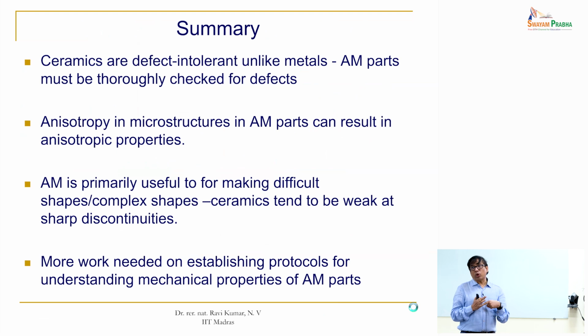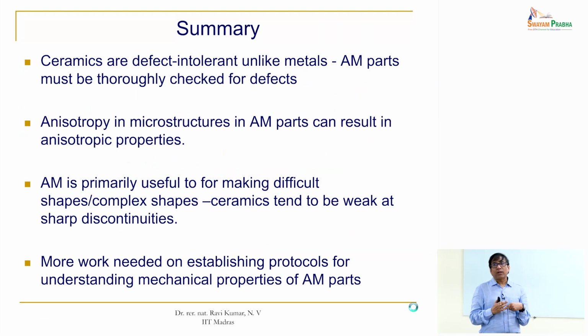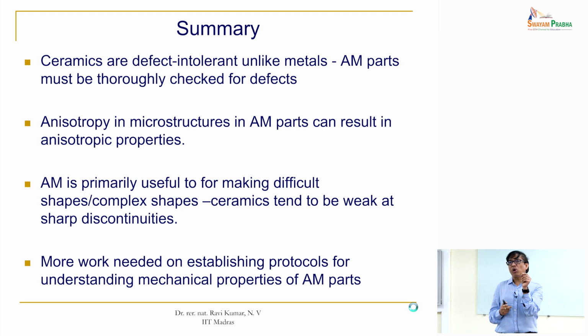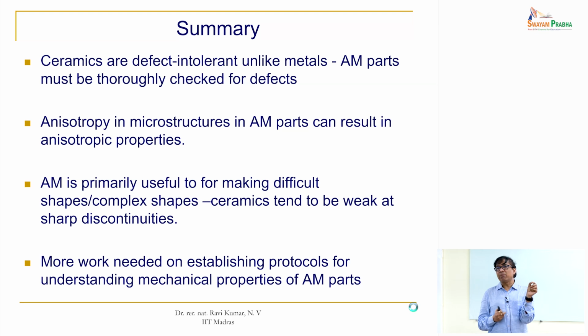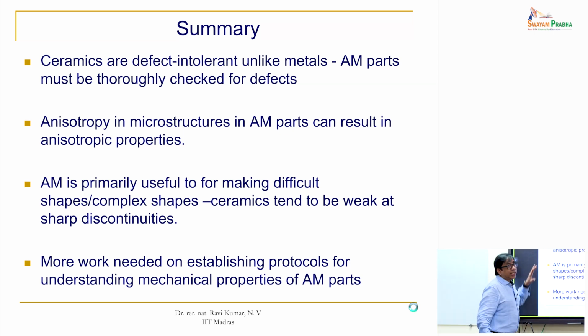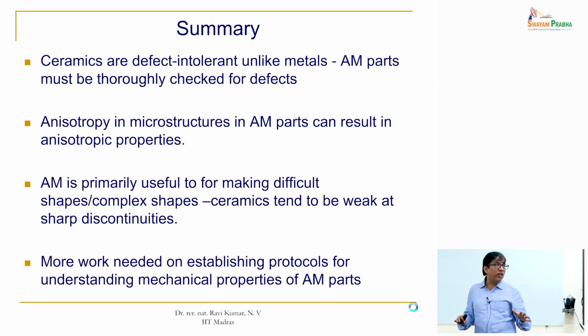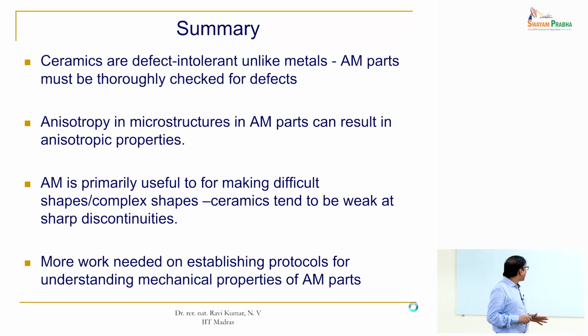Ceramics are defect intolerant, unlike metals. So you have to understand that even a very small defect in ceramics can be a point of initiation of failure, unlike metals. You have to be very cautious of that, and more so in additively manufactured parts, where you also have to look at flaws and thoroughly check for defects. Anisotropy in microstructures: depending on the manufacturing technique, it's important to look at the anisotropic character. And ceramics tend to be weak at sharp discontinuities, so you need to be careful of that.